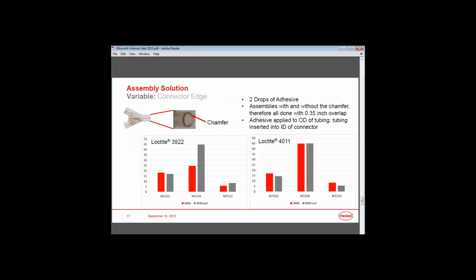And next, we took a look at the connector edge. So as you might have seen in a lot of connectors, there could be a chamfer on the leading edge, which is a tapered angle on the ID of that connector. So we wanted to see what would the results look like with and without that chamfer. So we removed it for the data that says without, and we kept it for the data that has it within. And you'll see again there's a minimal difference on the results with and without the chamfer.